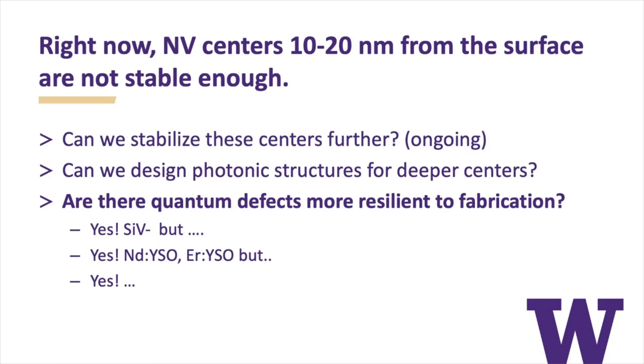And so the third one is, are there quantum defects that are more resilient to fabrication? Yes, the silicon vacancy minus is more resilient. It doesn't have this issue with being so sensitive to the electric fields, but it is sensitive to strain. And that means that you can't use electric fields to tune it. It also, for example, has to operate at dilution refrigerator temperatures because its spin coherence is not very good at liquid helium temperatures. It has to operate much colder. The rare earth doped crystals are also more resilient as well, but they don't have very strong oscillator strengths. And you can go through different defects. There's always a yes, but there's always a but.